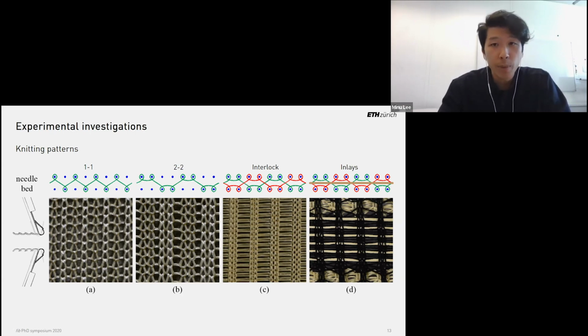And depending on the loop structure, it is possible to create different properties for the stretchiness or the density of the fabric. For instance, the patterns 1-on-1 and 2-on-2 here on the left side look very similar, but the interlock pattern here, figure C, is much denser. Additionally, it is also possible to integrate straight rovings into the textile, as can be seen as thick yellow yarns here on the far right side.